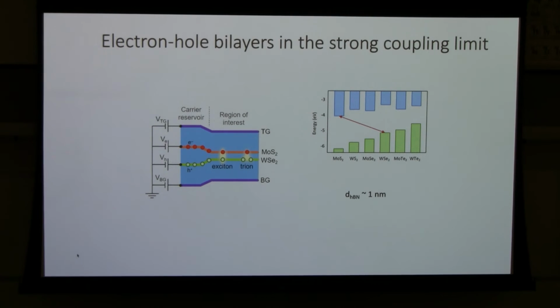So we modify our system a little bit. We now go to a MoS2 and WSe2 heterostructure, just because the band offset between these two is a little bit more favorable. Overall, they have a slightly smaller band gap. Then we can use a thin hBN and use a large electric field to close that gap to create an electron-hole bilayer. In this case, we will make the hBN only 2 or 3 layers, so it's around 1 nanometer.